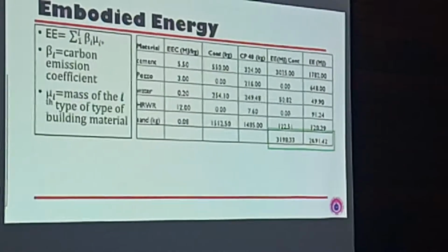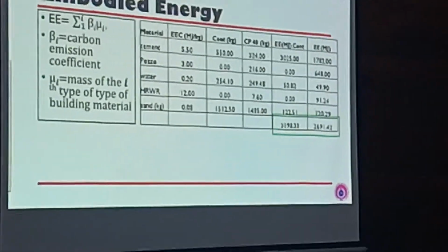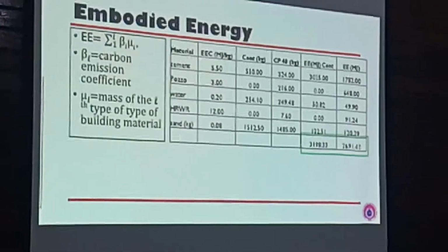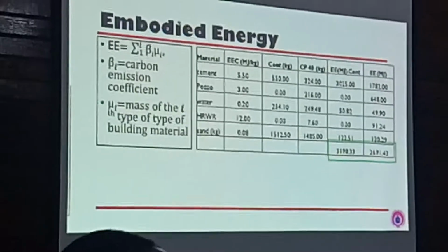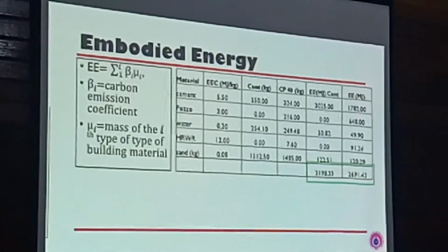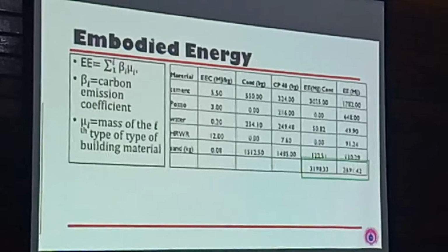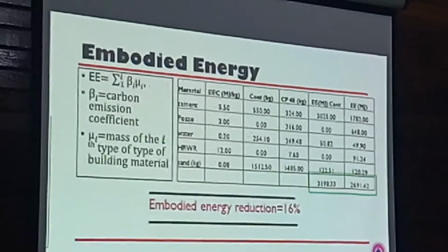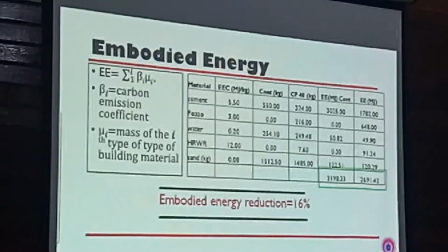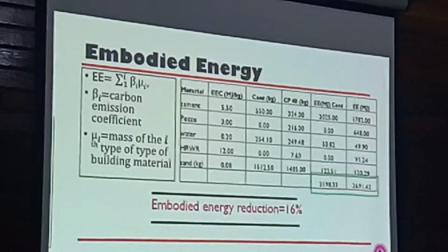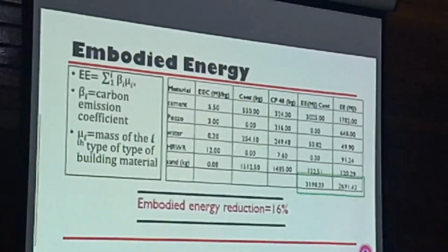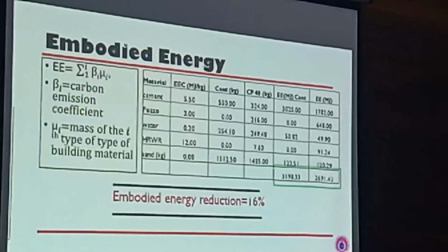So the higher the embodied energy, the higher the carbon dioxide emission. So of course you can see from this table that it is very good to introduce the pozzolans into your material because the embodied energy comes down. So we will see that the embodied energy reduction between the two was about 16%, which is very good.